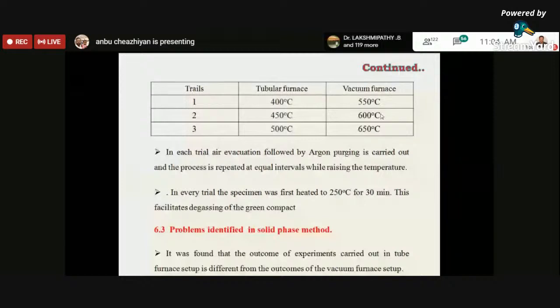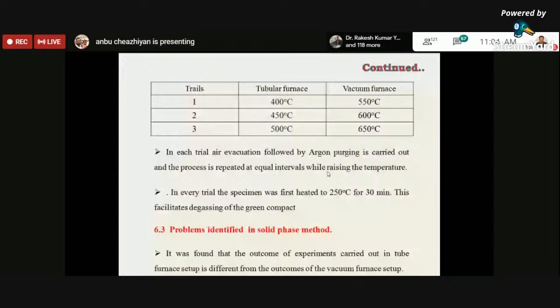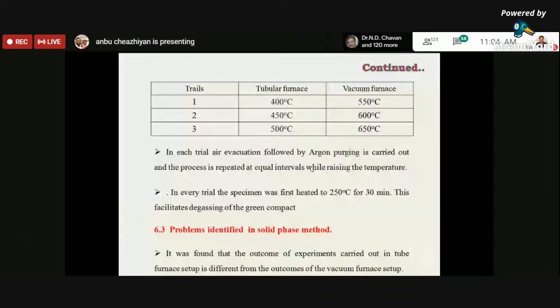In order to get a homogeneous mesh, you have to improve the sintering quality of the material. Okay, so what are the problems that we identified in solid phase materials? The sintering quality was completely increased in the vacuum furnace when compared to the tubular furnace. It was found that the outcome of the experiment carried out in the furnace setups is different. The tubular furnace surface is different from the vacuum furnace.